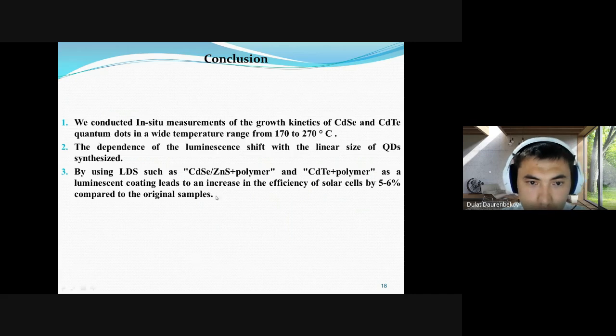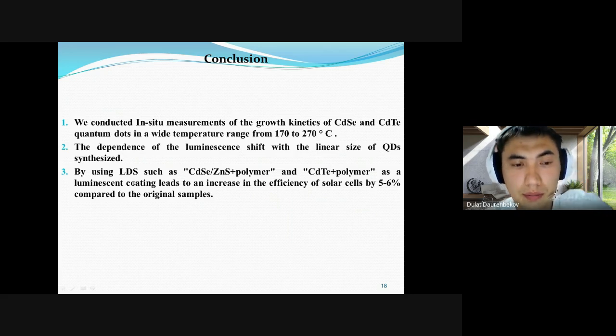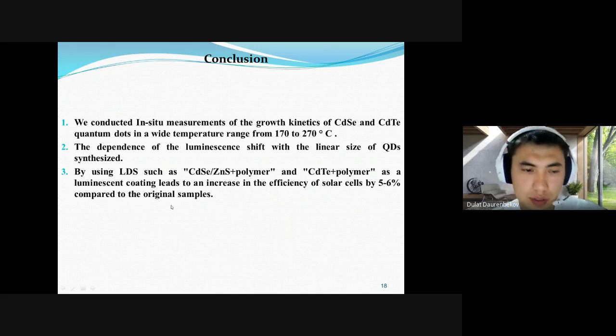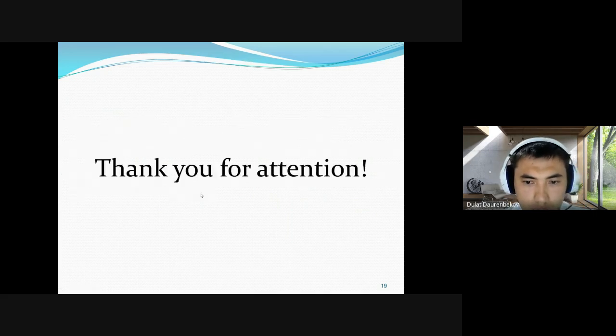Okay, in conclusion, we studied growth kinetics by an in situ method. We understand how to obtain the quantum dots with the characteristic peak luminescence at an exact temperature, and we know the size distribution by synthesis. In the end, we added the best samples for the LDS layer, luminescent downshifting layers. We use these systems: cadmium selenide zinc sulfide plus polymer and cadmium telluride plus polymer, and as you can see in the figure, the efficiency of solar cells increases by 5-6% compared to the original sample. Okay, thank you for your attention.